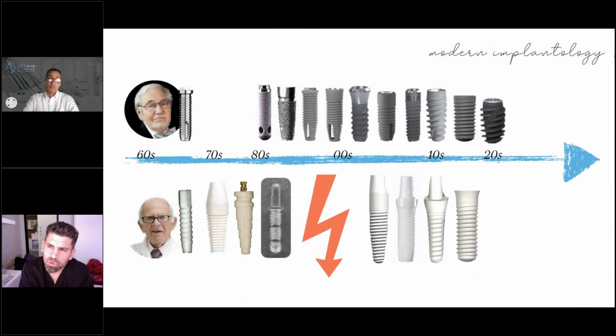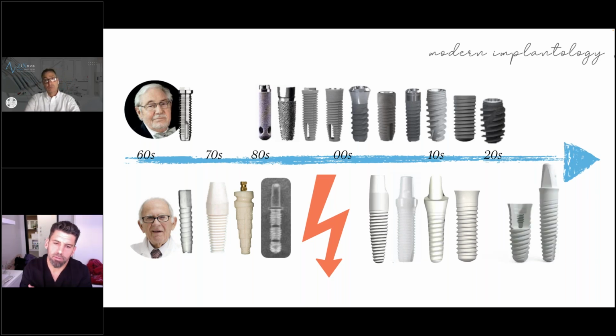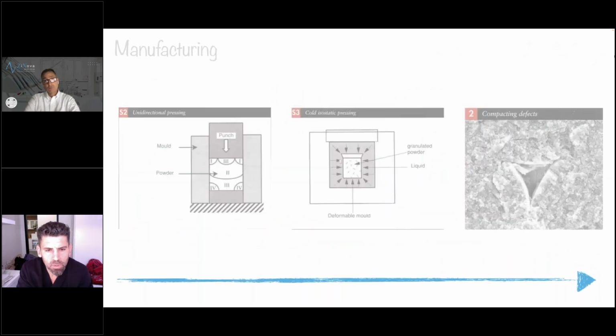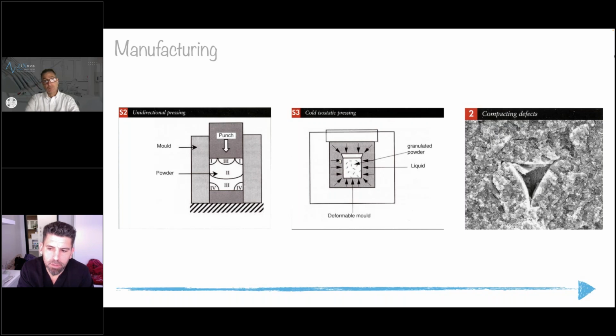So we talked about the evolution of implantology. We talked about the change in the material, the manufacturing of these zirconia implants has changed significantly to the point where now we are seeing implants that are being manufactured by injection molding. This is the latest technology in manufacturing of zirconia implants. So traditionally, the zirconia implants would be manufactured by pressing, whether it was unidirectional pressing, as you see here. Cold isostatic pressing was the next advancement, where you see the pressure coming in from all angles.